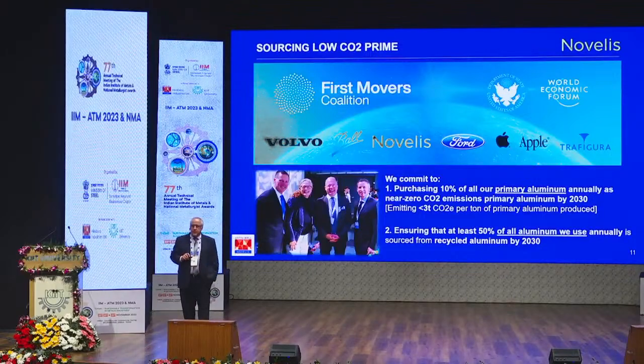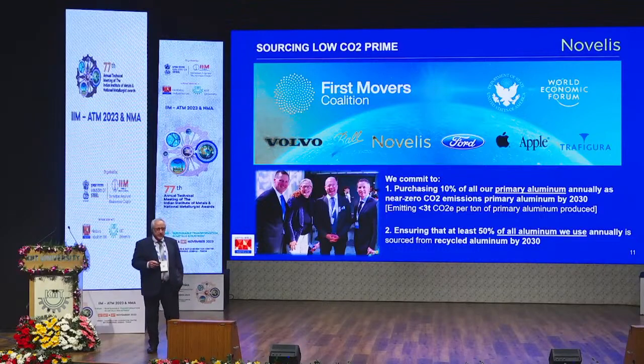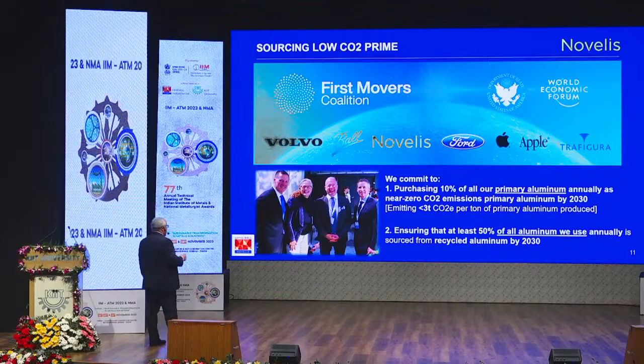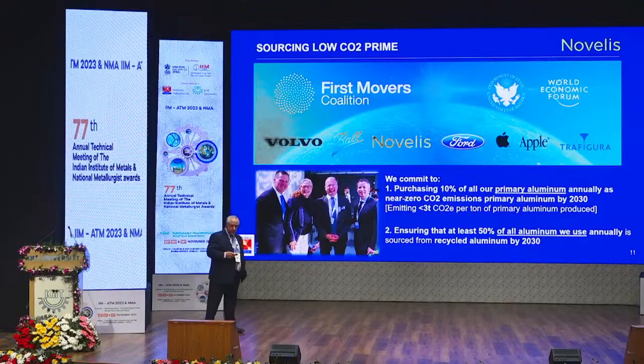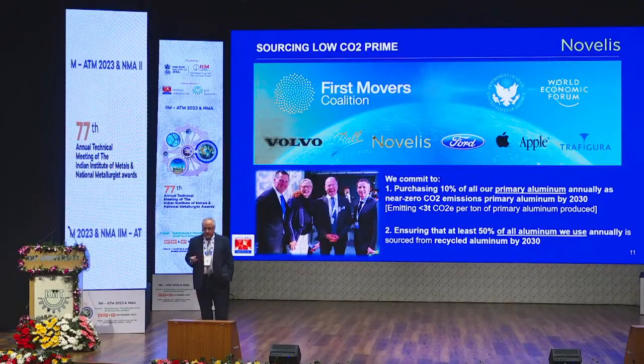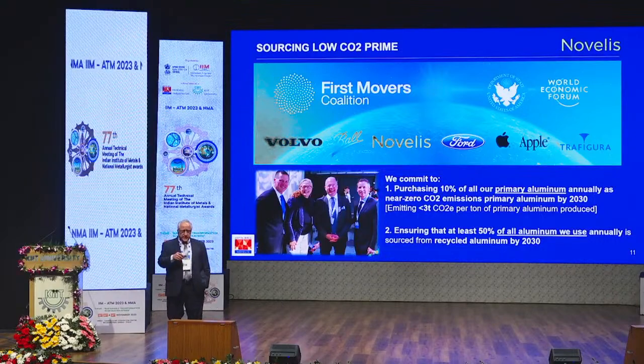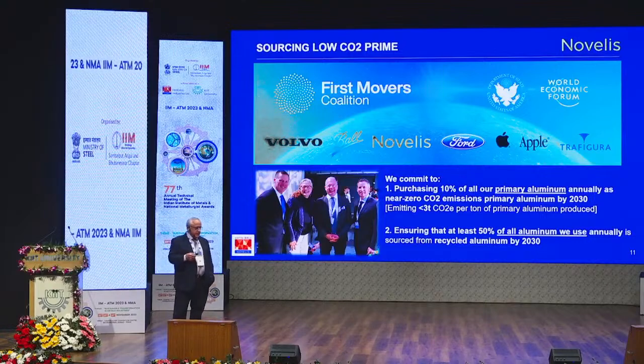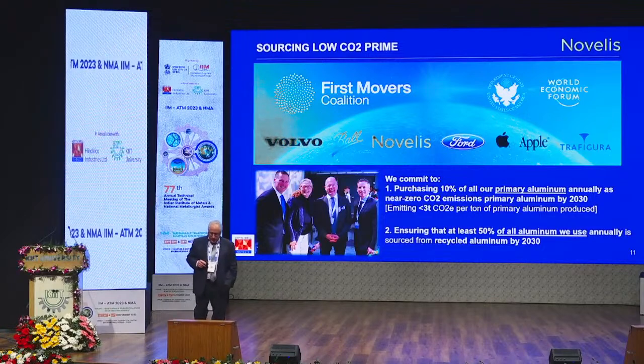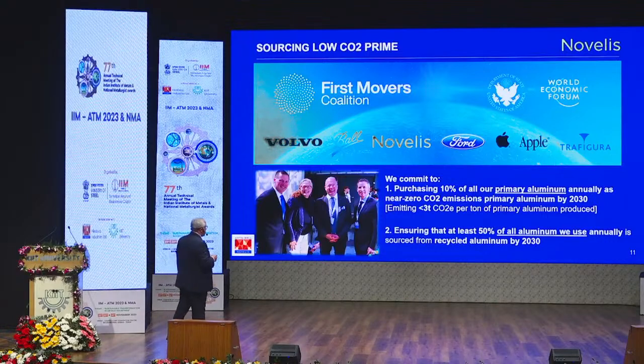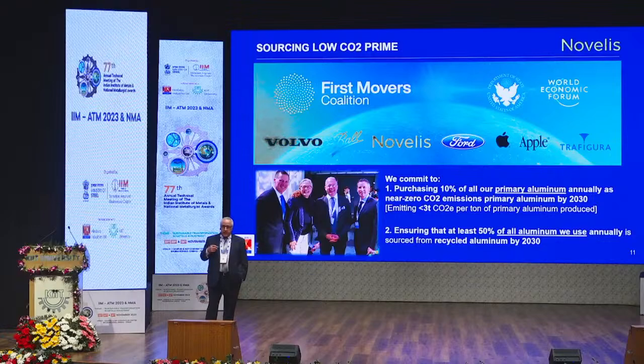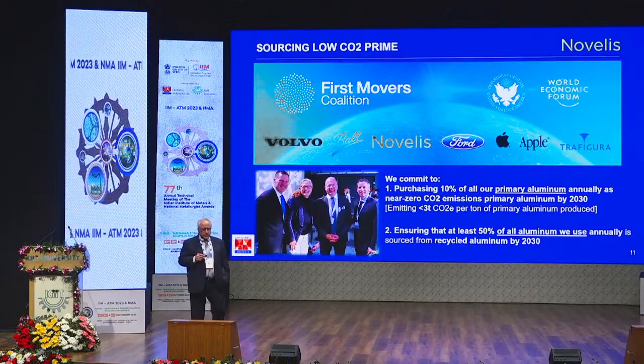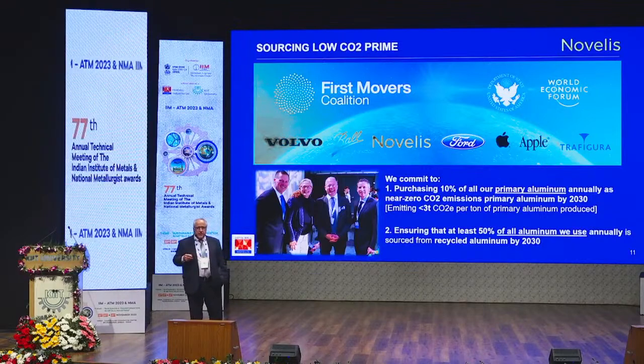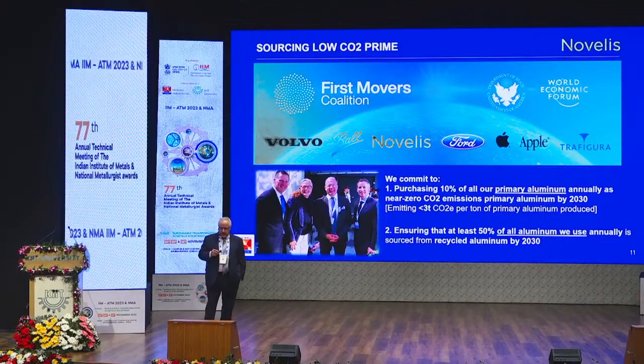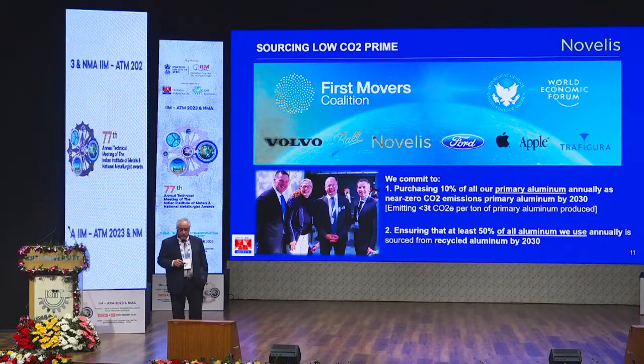Having said that, at the end, we believe there will nevertheless be a need for prime, and then we care to source this prime at the lowest possible CO2 footprint. We have engaged with, as you can see, very well-known companies in what is the First Movers Coalition. It's a spin-off of the World Economic Forum, and the participants really engage themselves as aluminum product producers. We have committed to purchase at least 10% of primary aluminum at a very low CO2 footprint, so net zero, below 3 tons per ton, which is typically half of a standard hydro-powered production today, more than 10% at the horizon of 2030, and to do that even more in the future.